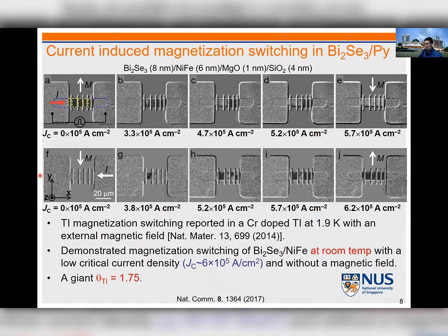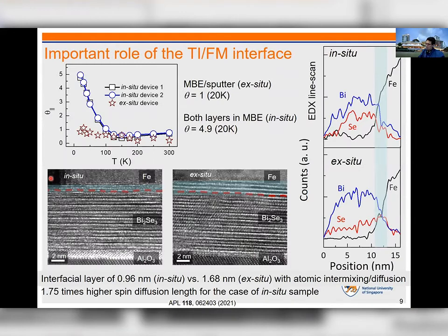And we tried to find out there must be some other role behind the scattered effective spin Hall angle values. Then we also got to know temperature also plays an important role because different groups reported the value at different temperatures. As we cool down the sample, we found the effective spin Hall angle maintains a similar value down to 100 Kelvin, but below 100 Kelvin, some devices show a giant, very abrupt increase of this effective spin Hall angle.